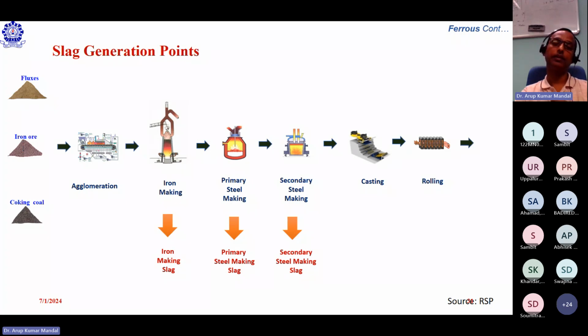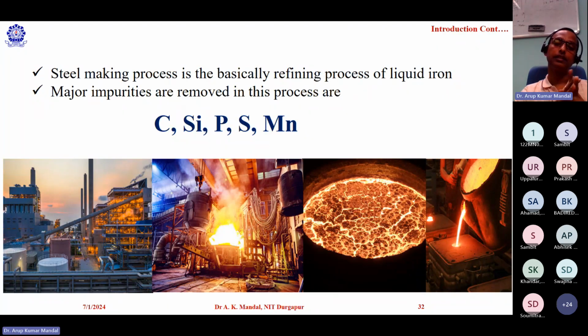For removing the impurities, what happens in the normal BOF process? Impurities are oxidized. To capture and eliminate these, it requires lime. Therefore, this lime is mixed with acidic oxides like silica, then it forms the slag. So can you replace this slag in the conventional iron making impurities removal process? This slag will generate. So we have taken some initiative to remove the impurities in a different way by the hydrogen plasma.